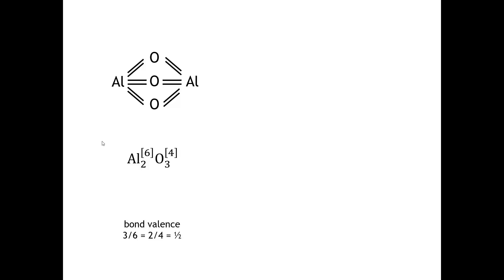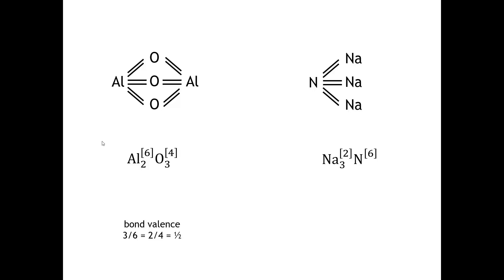For sodium nitride, nitride has a −3 charge and sodium is +1, giving the empirical formula Na₃N. Nitrogen's coordination number is oftentimes 4 or 6 — rarely larger than 6. Sodium is a large cation, typically anywhere from 6 to 12 coordinate. If we assume a coordination number of 6 for nitrogen, which is about as large as you would typically find, then the coordination number of sodium must be 2. The crystal chemical formula would be Na₃N with sodium being 2-coordinate and nitrogen 6-coordinate, and the valence of each bond is one-half.